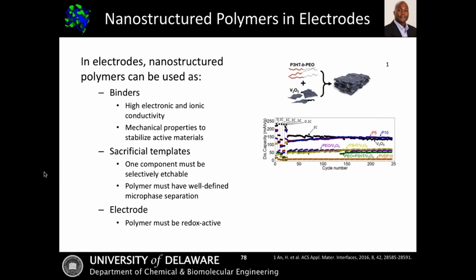In this case, then these polymers typically have to be redox active. And just one example of a potential material that has electronic and ionic conductivity is shown on the right side, which is a P3HT PEO-based block copolymer.